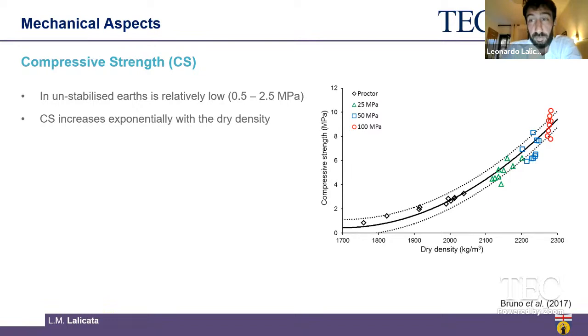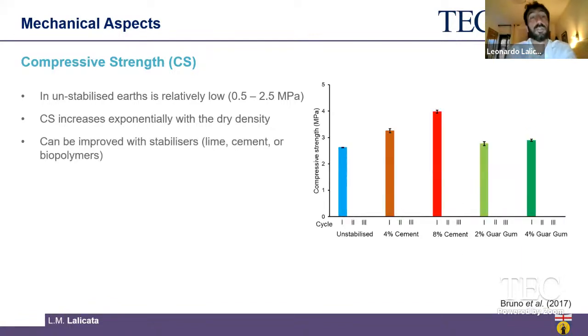An alternative to increasing the energy, because maybe you don't have the resources to do that, is to use stabilizers. And there are standard stabilizers such as lime or cement, but recently novel biopolymer stabilizers are also being developed. Usually you get an increase in the compressive strength with the stabilizers, which is less marked for the biopolymers. But in general, you get an increase in the compressive strength.